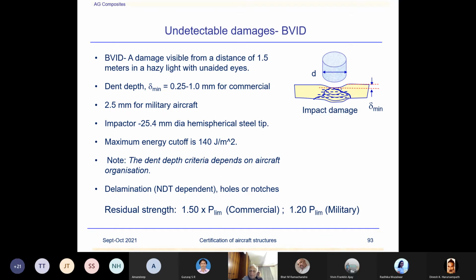Now, what you see from the diagram, as I was talking, in metal, if this is a metallic sheet, when you create an impact, the dent will be visible and there won't be any damage like this one, what you see. But in composites, this is typical. The impact would have created enough damage which is not visible on the surface. No fiber damage or anything, but internally, there could be delamination and fiber damages. So this is a difficulty with these composite structures. The inside damage, but no outside damage may be visible.